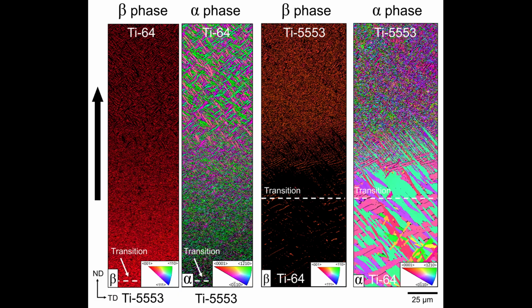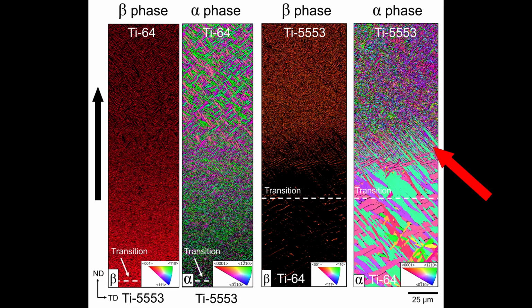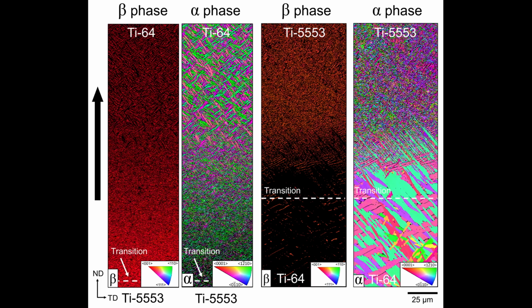These electron backscatter diffraction orientation maps show the individual beta and alpha phases when the Ti-5553 is transitioned into Ti-6-4 and vice versa. In the latter alpha phase map on the far right, in the first microstructure transition step, that is, the first layer deposited after the wire feed was switched to Ti-5553, a series of heterogeneous parallel alpha laths were able to grow uncontrolled into the matrix of the Ti-5553 due to the sudden change in alpha-beta phase stability.